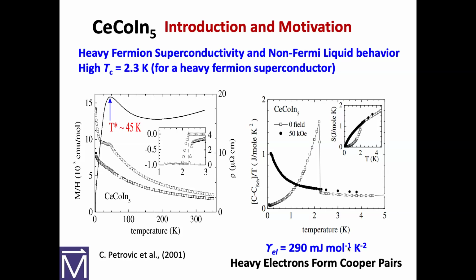So the reason I started that way is that when the iron-based superconductors were discovered and people are accepting that it's s-plus-minus in the pairing symmetry, that's the same symmetry as the underlying lattice. Some of you may remember the definition of an unconventional superconductor was that the pairing symmetry of the order parameter was a lower symmetry than the underlying lattice, right? That's not true with the iron-based superconductors. And so I've been studying this for a little bit longer than 2 years. I think this may be my swan song physics stuff.